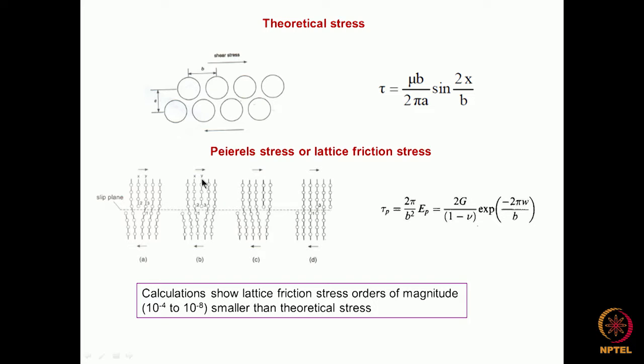And when this bond is being formed like this, the bond is being broken here. Now if you see, this is what has happened: this has become the extra layer. Initially the extra layer was here. What have we done? Only bonds are being broken and joined. When this sort of process is occurring, it appears as if the extra layer which was here has shifted to this position. When finally this bond is broken and joined here, that extra layer has just come out of the sample surface.